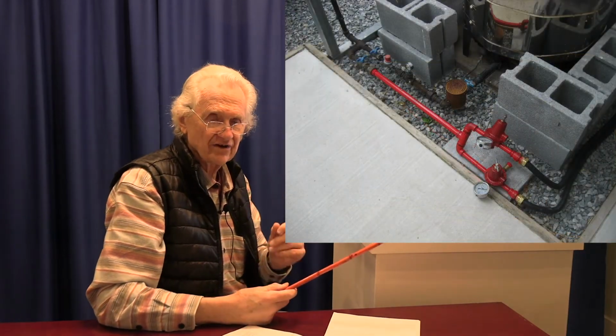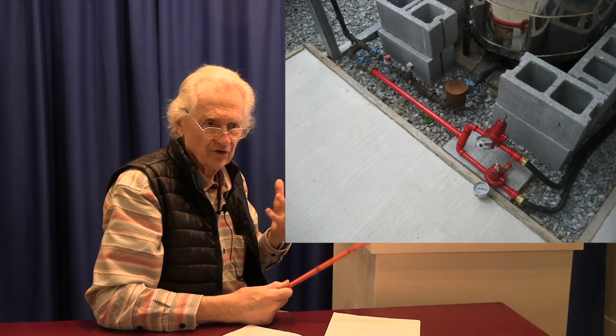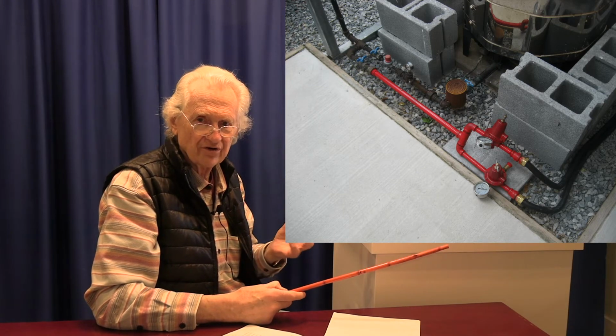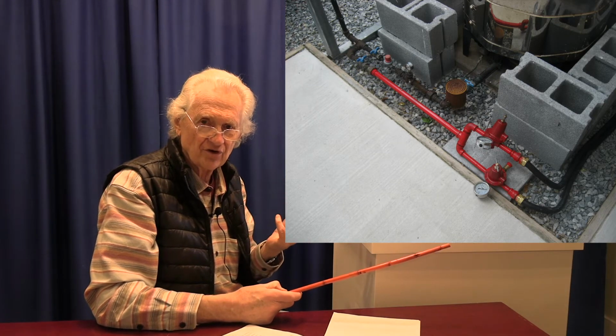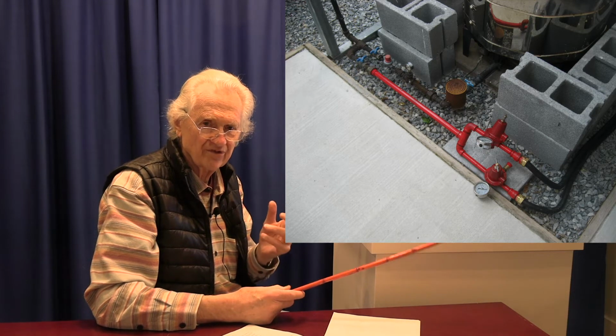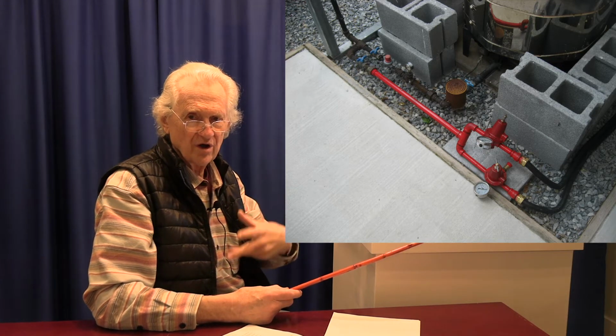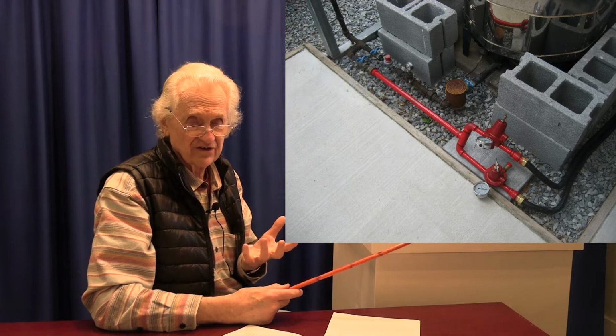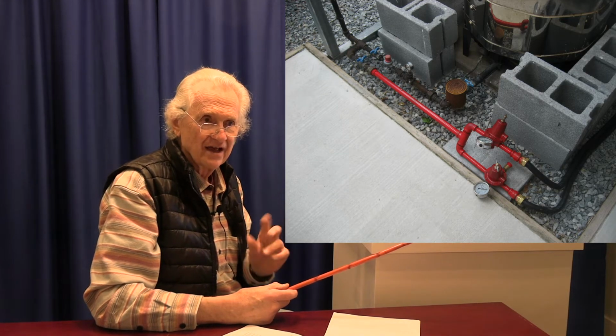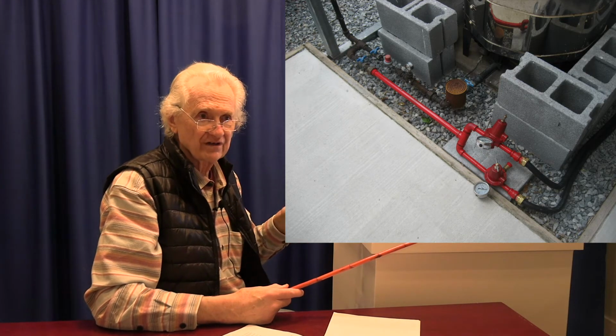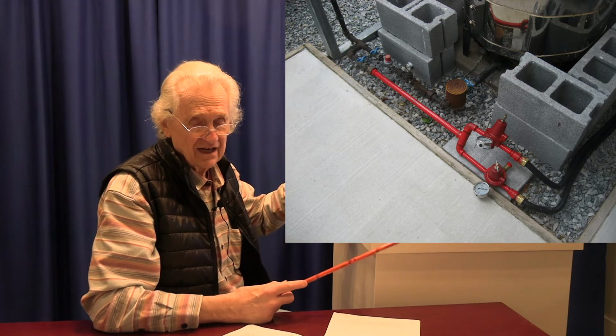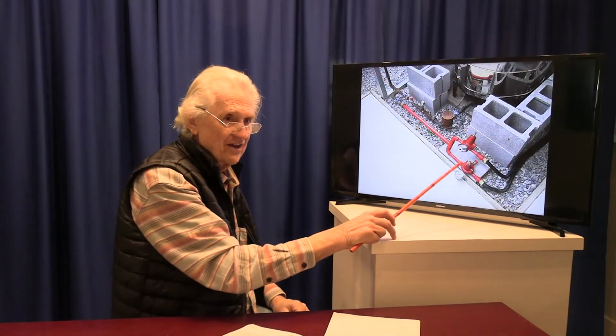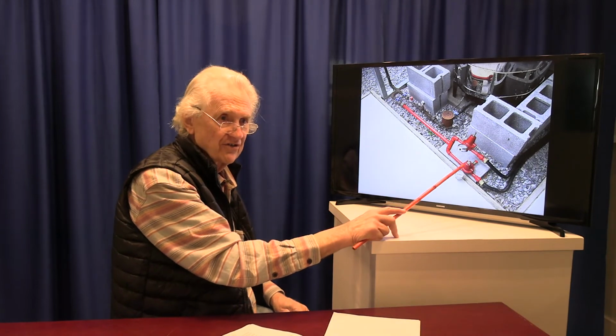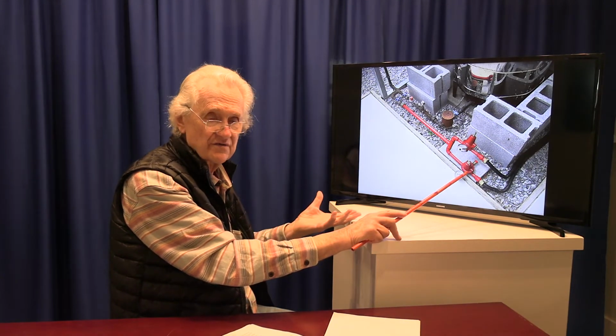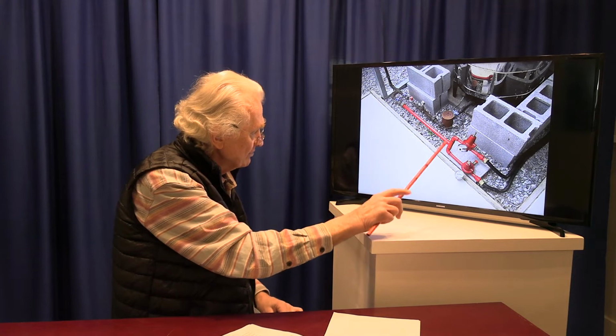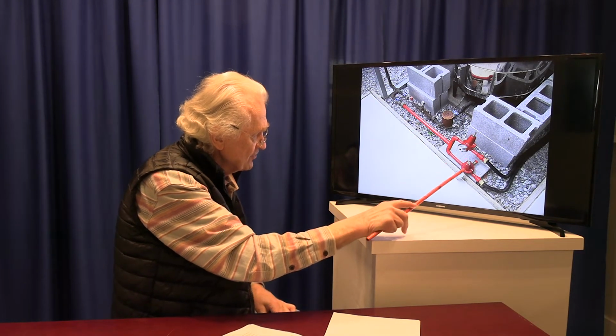Instead of having 1 regulator, again, I've run into situations where during a firing, if something happened to one burner, let's say you started to get carbon deposition on a burner, or one burner starts to have problems, you might need to make adjustments to the one burner. You might want to change the pressure, for example. Well, if you only have 1 regulator, you can't do that. So I know this is a little bit of a luxury, but we wanted this to be a Cadillac kiln. So we decided to have separate regulators, 1 for each burner, so that again, we'd have complete flexibility in terms of adjusting the burners. So this is all black iron piping with the 2 regulators.